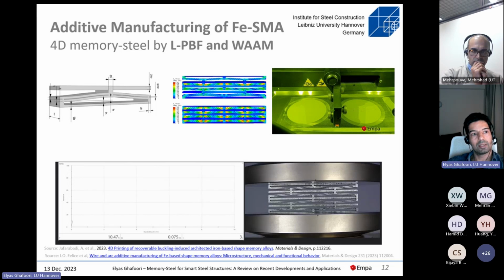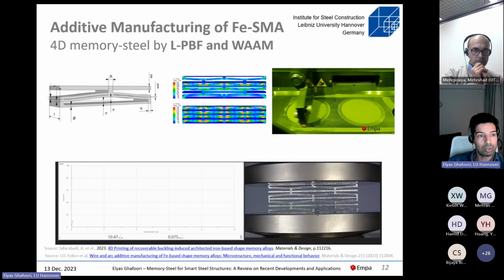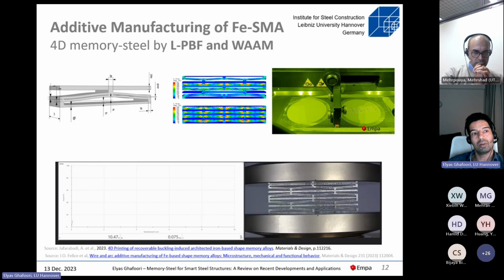And so there are billets, and there is a hot rolling process, the typical hot rolling process that we have for these beams, girders, all the steel girders you see around you. Normally they are hot rolled up to 3 millimeter thickness of the strip. And then from 3 millimeter to 1.5 millimeter strip thickness, we go with a cold rolling process, which is also a typical process. That's the reason the alloy is cheap: you can use traditional steel manufacturing processes. You don't need special equipment, furnace, and so on. And it doesn't have to be done under vacuum. That's very important. You can do it at atmospheric condition.